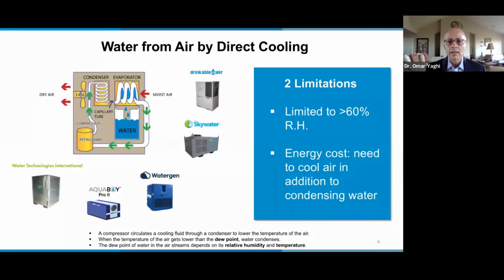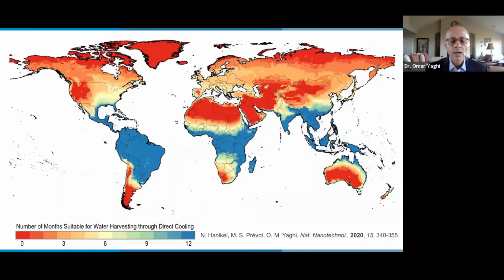So the idea of harvesting water from air is not new. There are products out there, as you can see here, where this could be done. However, the limitation is that they all work very well when the humidity is high, above 60% relative humidity. And anything below 60%, there's such a tremendous energy cost that they do not work. So you can think of these as working only at high humidity. And there's absolutely nothing out there that works at lower humidity, especially humidities where these red regions are usually most of the year experience. So it's these regions where we need materials that could harvest water from air in an energy efficient way.